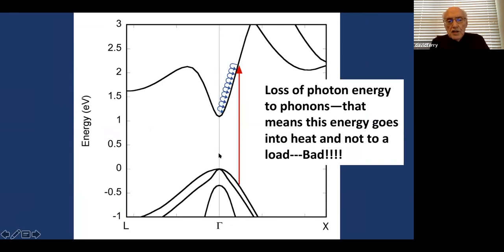It's got a gap just over a volt, about 1.1 volts. So if I take a 2.5 volt photon, it excites an electron out of the valence band here into the conduction band. Now at this point, it's got a lot of high kinetic energy. And so what it promptly does is it emits a lot of phonons. That's this bouncing thing. And the phonons are about 35 millivolts in energy. And so they're going to emit enough phonons to get down here to relax at the bottom of the band. That's the relaxation process by phonon emission.